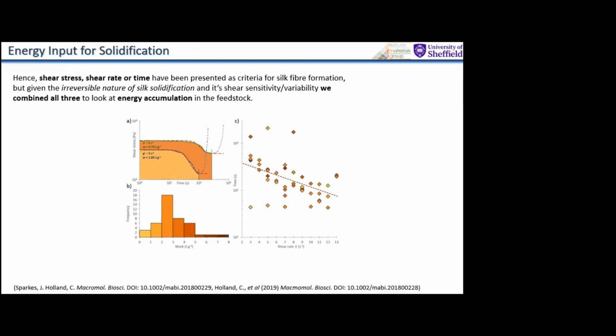And what we're taking away from here is that we're basically spinning silk. We are subjecting it to an increasing flow rate or shear stress that we can see here. And over time, it will transform from a liquid into a solid. And if we look at how much energy or how much work is required on average for each of the samples, it's hovering around about this 2 to 3 joules per gram. And the work to solidification clusters around that 2.75 joules per gram.